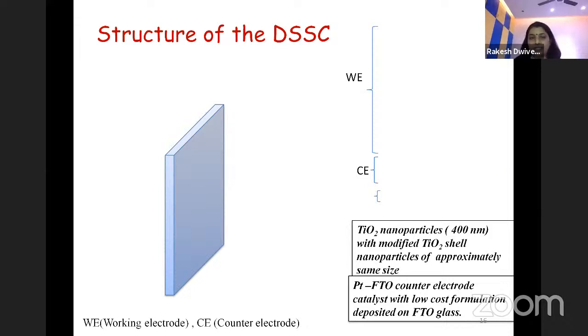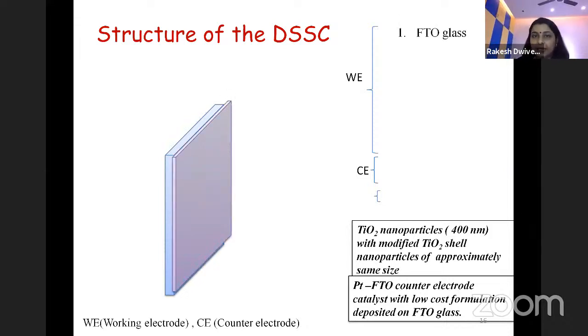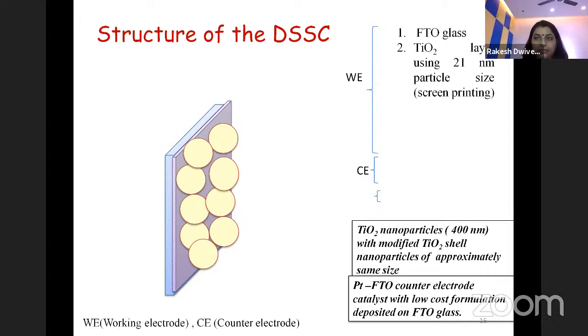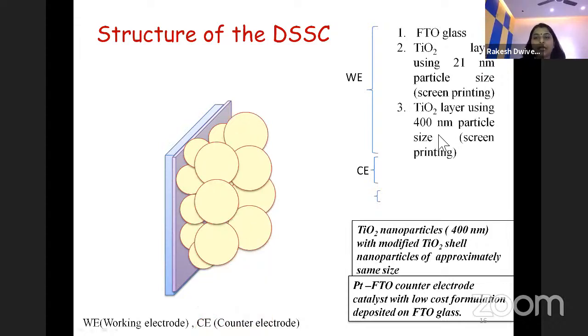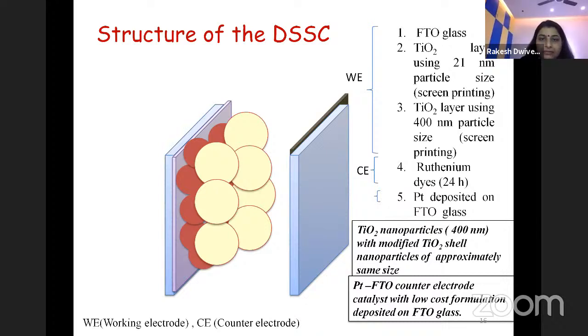As we have seen the structure of DSSC, it has a working electrode, on which we make conducting glass by depositing a layer of fluorine doped tin oxide, on top of which we deposit a layer of TiO2 nanoparticles. We make the paste of TiO2 nanoparticles of size 21 nanometers, and we deposit it on top of this working electrode. On top of which we deposit a layer of 400 nanometers. And this is the counter electrode, which is also a conducting glass, on which we deposit the platinum, and between these two we inject the electrolyte.